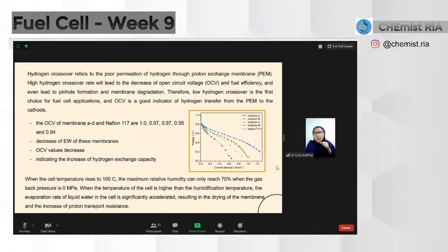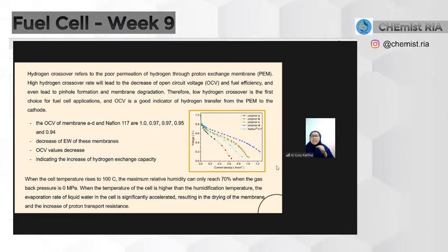As shown in the figure, we can see the OCV of membranes A to D and Nafion 117 are 1.0, 0.97, 0.97, 0.95, and 0.94 respectively. With decrease of EW of these membranes, their OCV values decrease, indicating the increase of hydrogen exchange capacity.